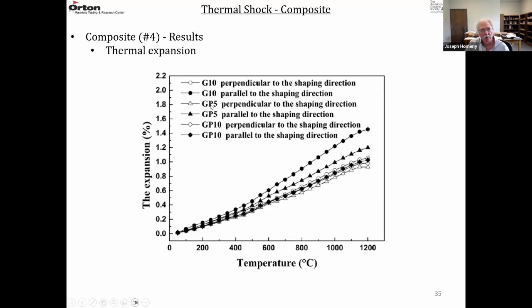Then when you add these pellets, which are the crushed flake graphite and the MgO, GP5, the triangle is perpendicular to the shaping direction. That's the open triangle, and the solid triangle is parallel. So the solid triangle is down here, the open triangle is over here. So that gap between the thermal expansion in the two directions is decreasing. And then finally, GP10, open triangle perpendicular to the shaping direction and a solid triangle parallel. They're basically on the same curve here. So the addition of these pellets of the crushed material decreases the anisotropy in these refractory bricks.